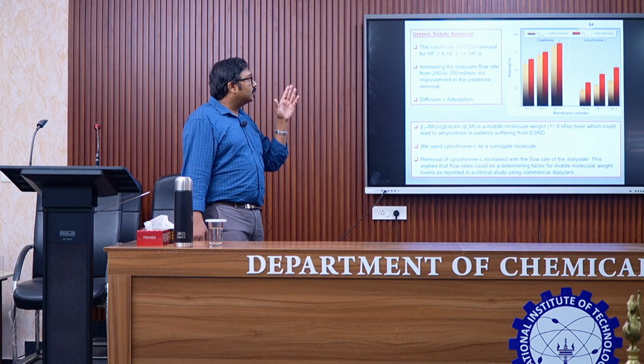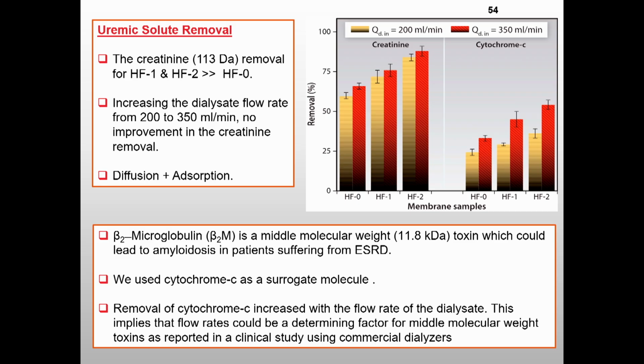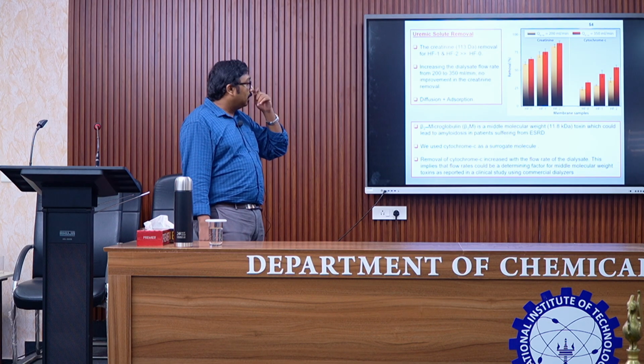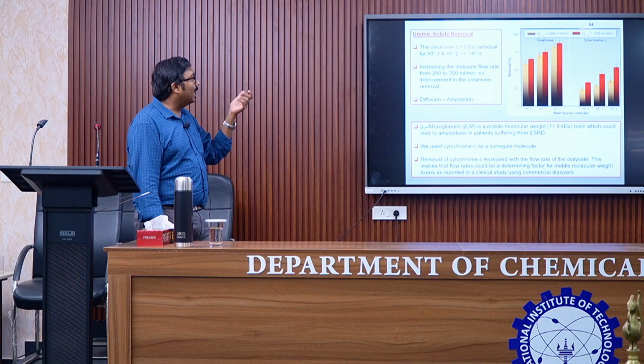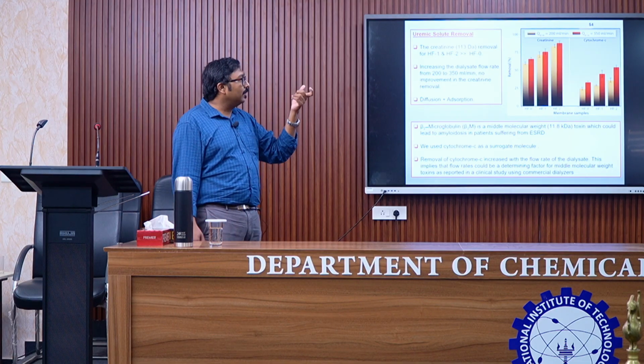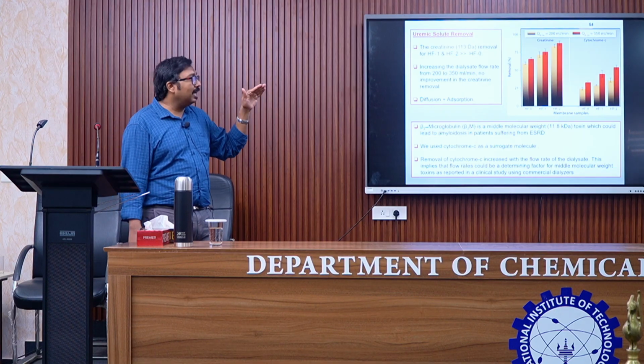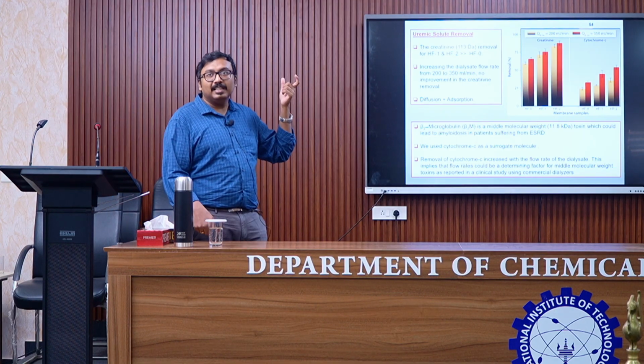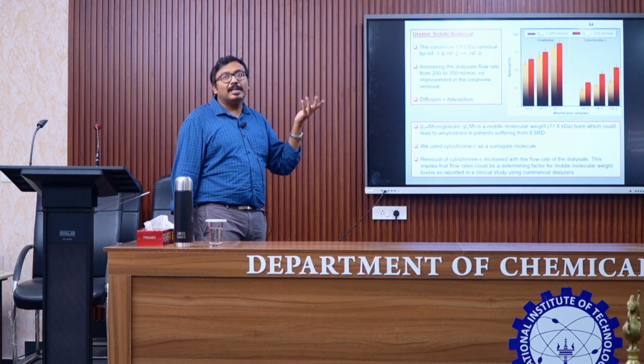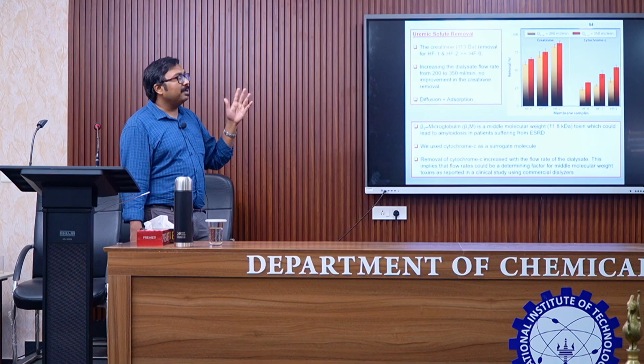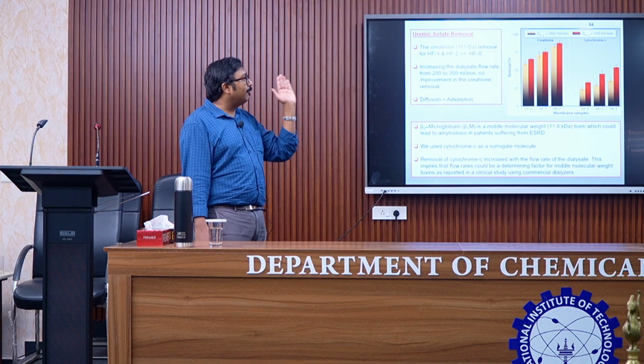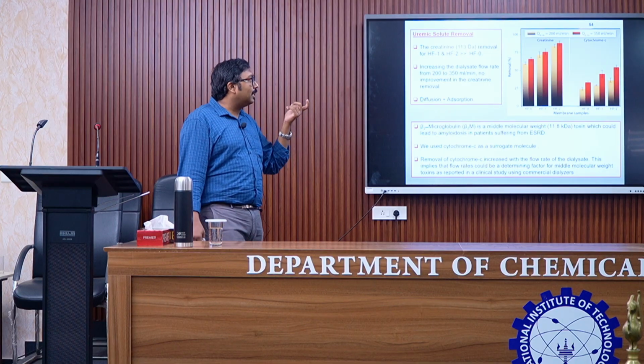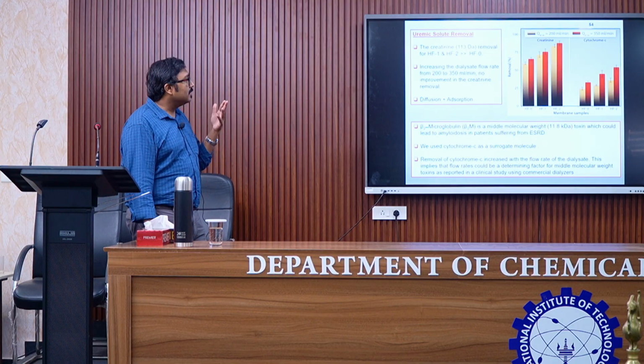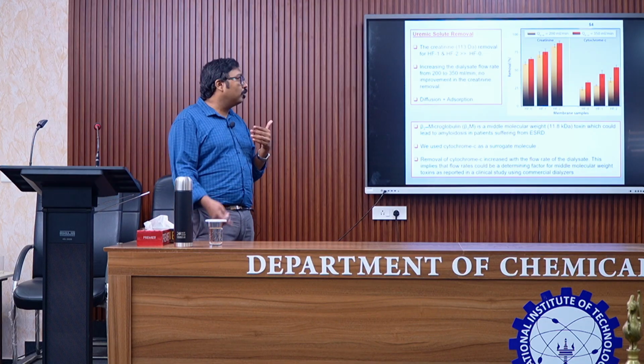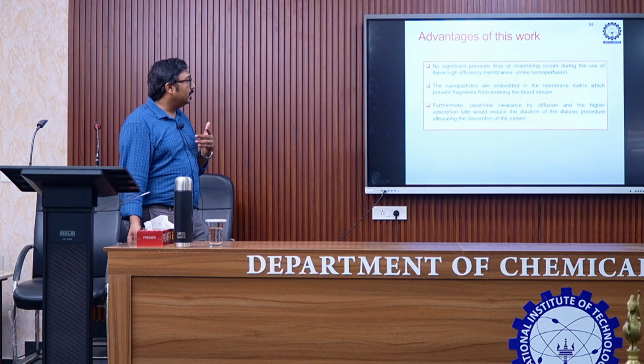And then we did the run. Here creatinine and cytochrome C removal was evaluated, again in counter current mode. You can see the modified membranes, the membranes with the carbon nanotubes, had higher removal of creatinine as well as cytochrome C. The removals are different because creatinine is around 113 Dalton and cytochrome C is around 12,000 Dalton, so the removal is less. That is as expected. But if you increase the flow rates of the dialysate, we saw a slight improvement in performance. That is also good, because this is within the operational parameters approved by WHO or the US government.